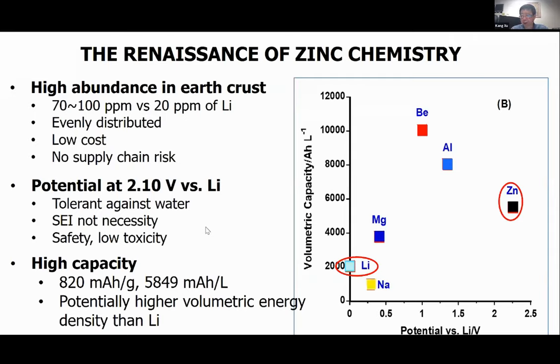However, because of its divalent nature, it compensates in part for the energy density, especially when you look at the volumetric density. If we assume that 100% of the zinc metal can be used and is reversible, the volumetric density of a zinc metal-based battery is actually higher than lithium and higher than sodium. Of course, by weight, it's much lower.